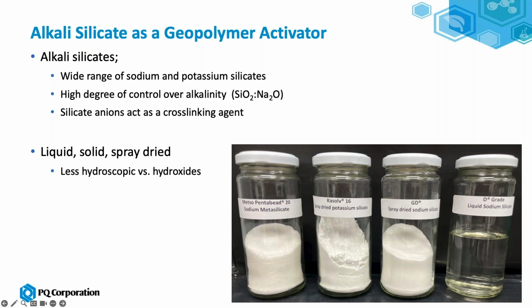Why we're involved or interested is the need for an alkali. Alkali silicates are one of the preferred forms versus, say, caustic, and there's a few reasons for that. We manufacture a wide range of sodium and potassium silicates, and we can control the alkalinity based on the ratio of silica to alkali. And because of that, you can customize it to whatever your aluminosilicate source is. And then the silicate anion acts as a cross-linking agent within the geopolymer to impart further strength. So this gives a lot more flexibility over, say, sodium hydroxide or potassium hydroxide.